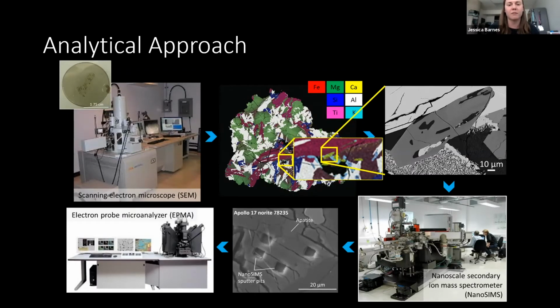This is probably not surprising to a lot of people. It's a pretty standard way to go about analyzing volatiles in samples. I usually take a thin section, and then use a scanning electron microscope to take X-ray maps using energy dispersive spectroscopy that relate to specific elements, and then I overlay those to form a mineral composite map like the one you see in the center, where different elements are indicated by different colors and then overlain.